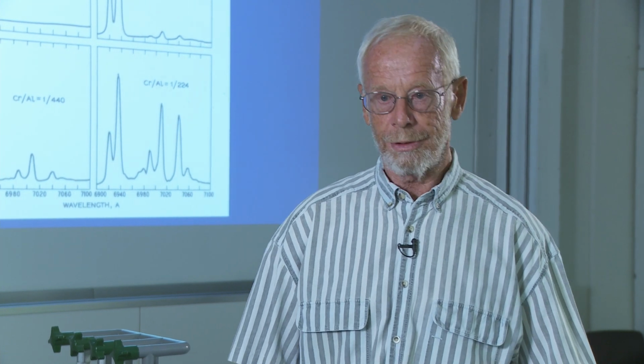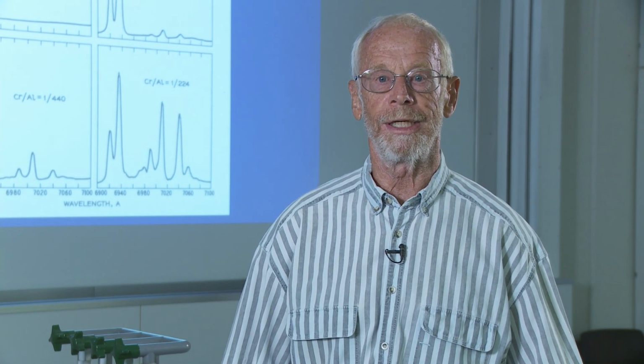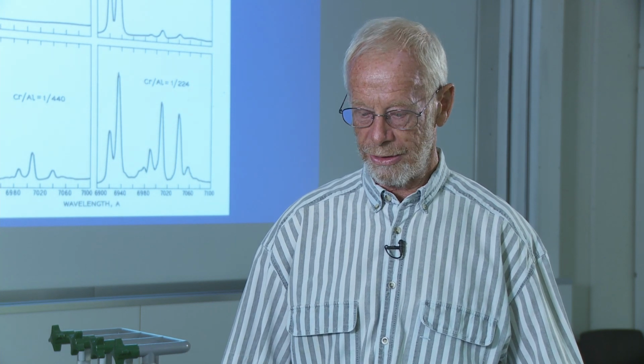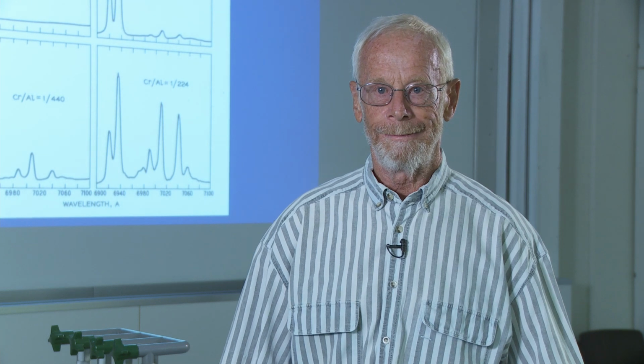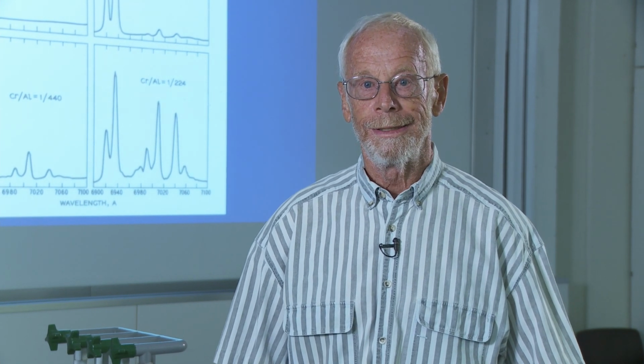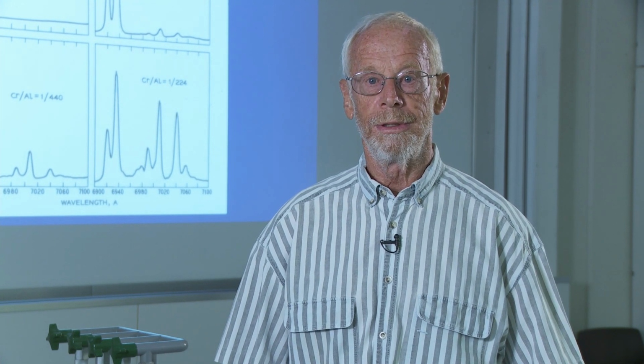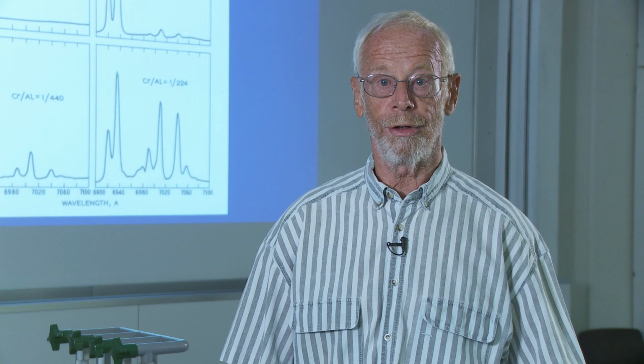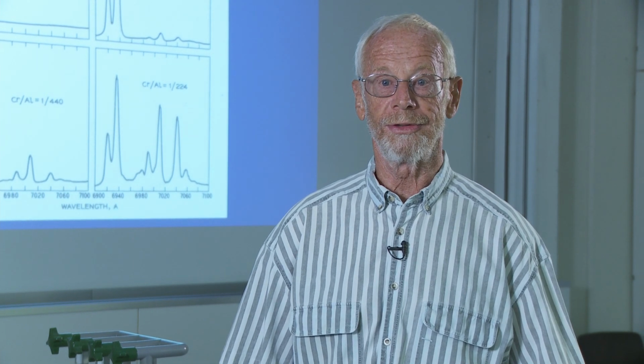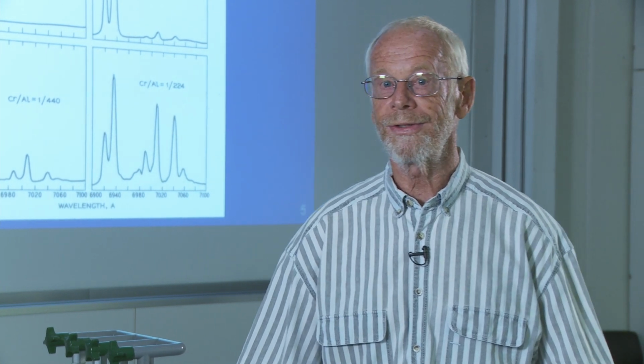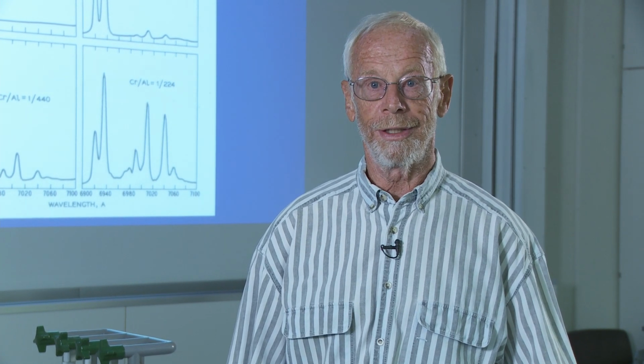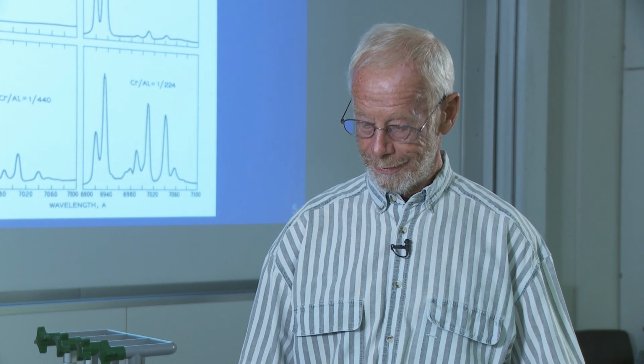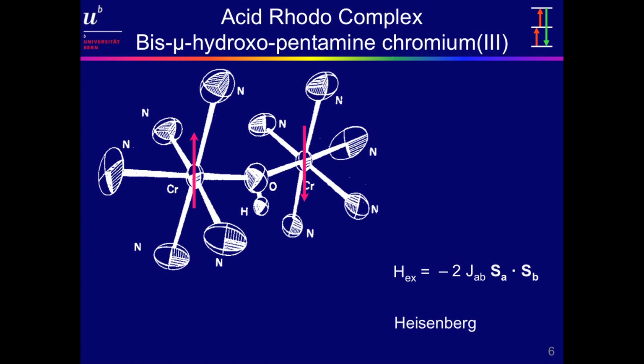But the problem with the corundum structure is that there are many different types of dimers, and the spectra of these species are superimposed. It's very difficult to take them apart. So I suggested to Jim that I would make a material containing only one type of dimer and no single ions. He had never heard of this, but he was interested. So, being a trained coordination chemist, I put on the lab coat and made this dinuclear chromium complex. A hydroxo bridge between the chromium ions, ammonia ligands completing the coordination.